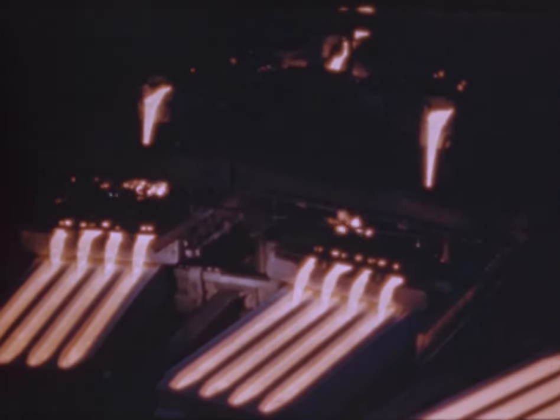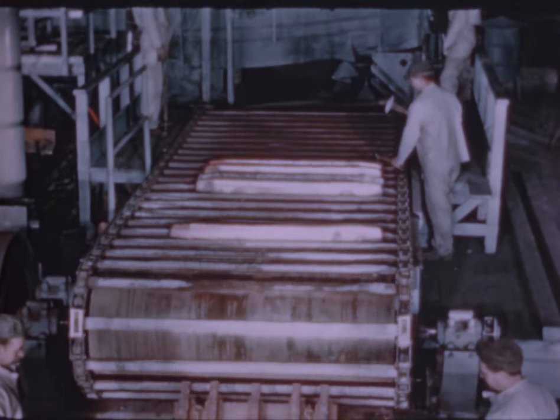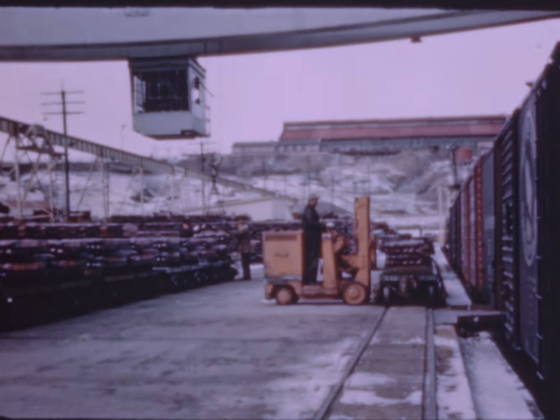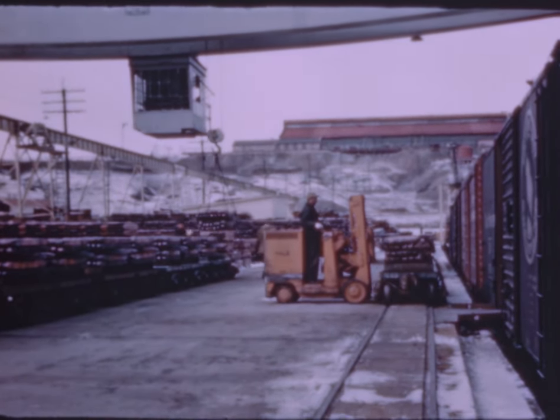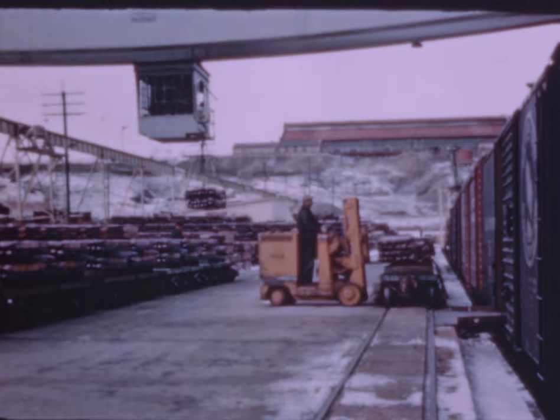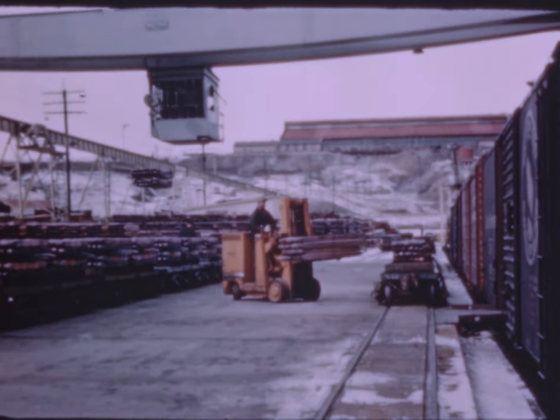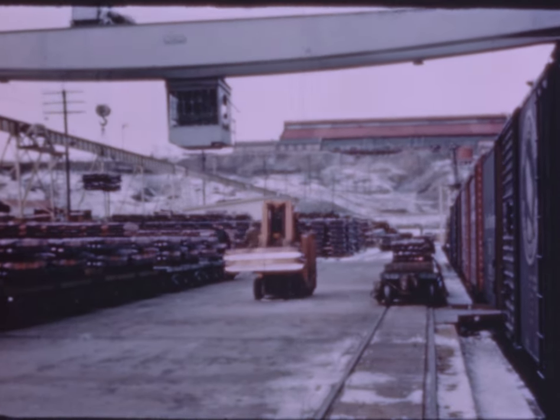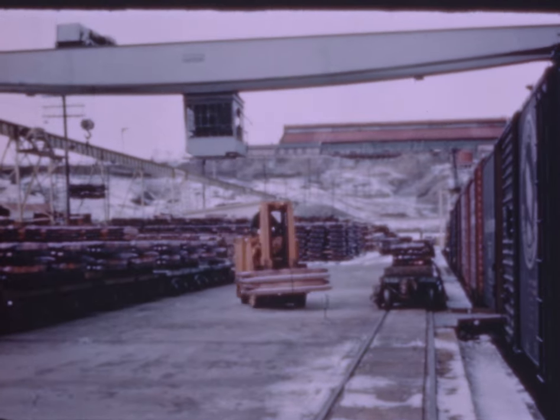Using two ladles, two molds are poured at each spotting of the wheel. After solidifying, the bars are cooled in a water bath and brought up on a sweep conveyor for inspection, identification painting, and stamping of the furnace charge number into the metal. Normally, over 60% of the electrolytic copper shapes produced at Great Falls is shipped to the company's wire and cable subsidiary for fabrication into electrical conductors.